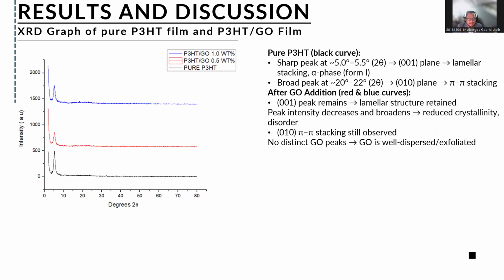the 001 plane will remain, which means the lamellar structure is retained. But the peak intensity will decrease and broaden, reducing crystallinity and indicating disorder due to the GO. But the 010 peak indicates that pi-to-pi stacking is still observed, and there is no distinct GO peak, which means that it is well dispersed onto the polymer surface.